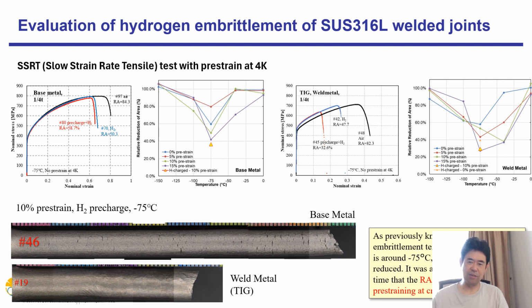Hydrogen embrittlement is always a big problem in many materials that are applied for hydrogen-related facilities. However, 20K, the boiling point of hydrogen at one atmosphere, is too low even for hydrogen moving into the inside of the iron lattice. So minus 75 degrees C is the most deteriorated temperature. This is our opinion. This is the competition of two factors.